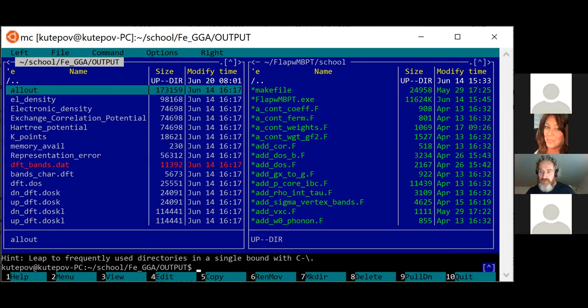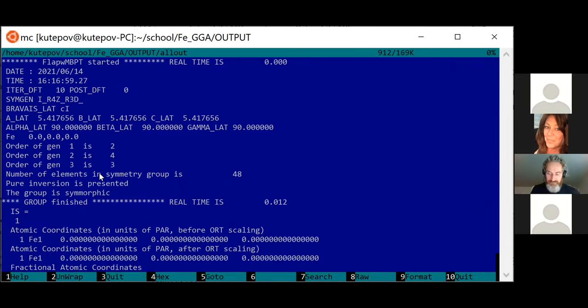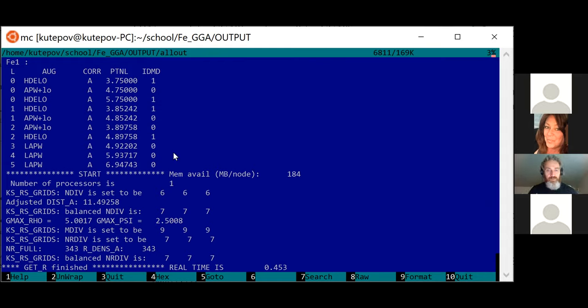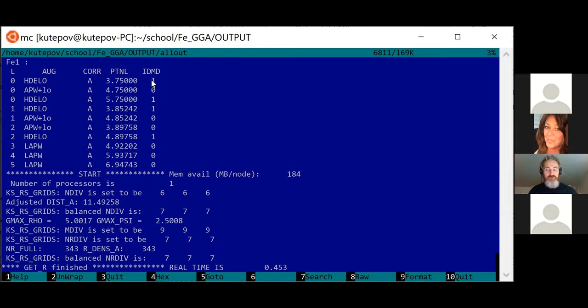There's a question about IDMD. This variable is the choice of how the linearization energy is selected. If it is zero, it is selected as the center of mass of the occupied band — the old-style choice. If it is one, it corresponds to a specific algorithmic derivative that changes depending on the potential parameter PTNL. This parameter is: principal quantum number plus one half, minus the arctangent of the logarithmic derivative divided by pi. The integer part always corresponds to the principal quantum number, and depending on the value of the logarithmic derivative, it will be close to one number or the next. This is a convenient way to define the logarithmic derivative.